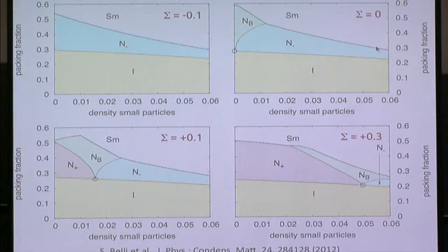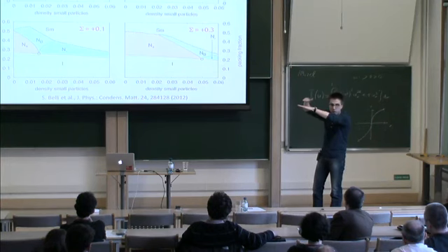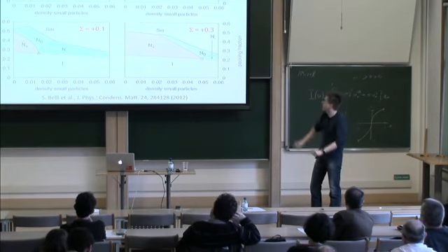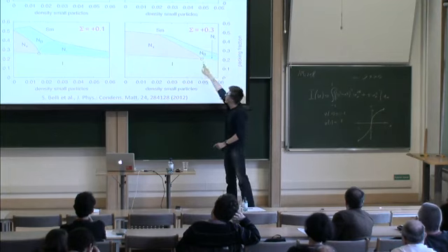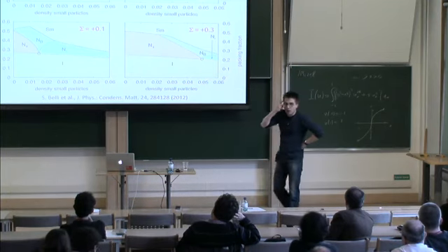But when the attraction between the particles becomes stronger, it's energetically favored to have stable phases in which there is a higher shared surface between the particles, due to their configuration. So they tend to prefer oblate ordering. And again, as a competition of these two effects, you have the appearance of this Landau critical point.